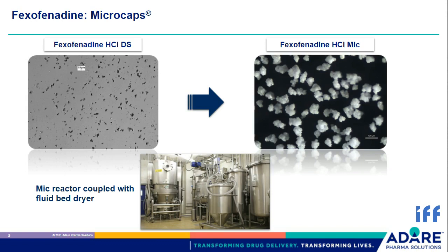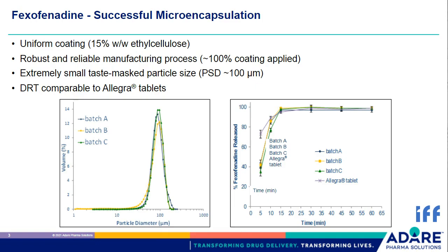Despite the small particle size and large surface area, the amount of coating required is quite low, in the range of 15%. The coating deposition is confirmed to be quantitative, therefore highly efficient. Particle size is in a range where grittiness perception is minimized, and the dissolution profile is superimposable to the profile of an immediate release form, even if the drug release in the first minutes after the administration is much lower to ensure taste masking.